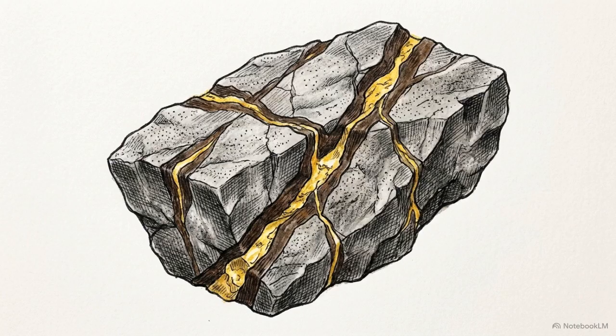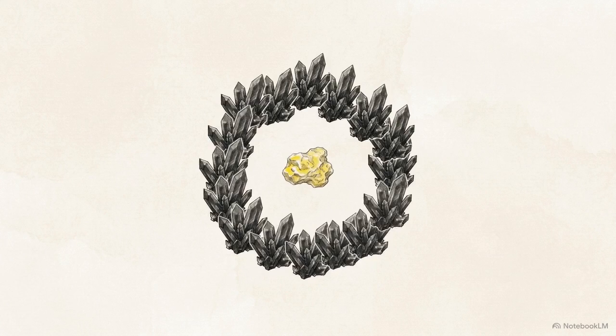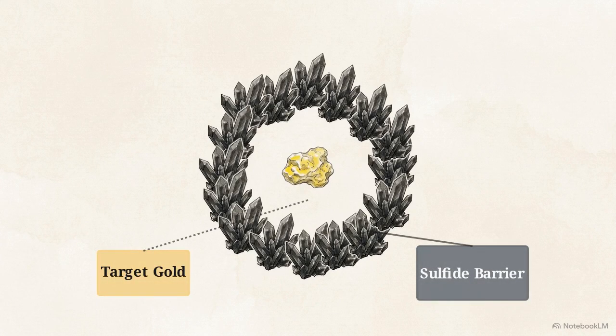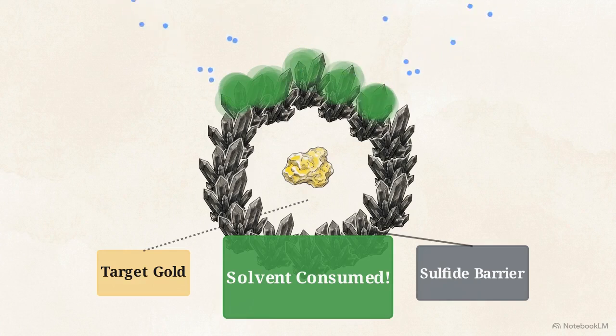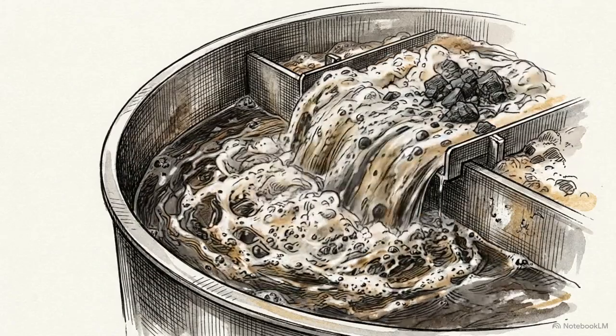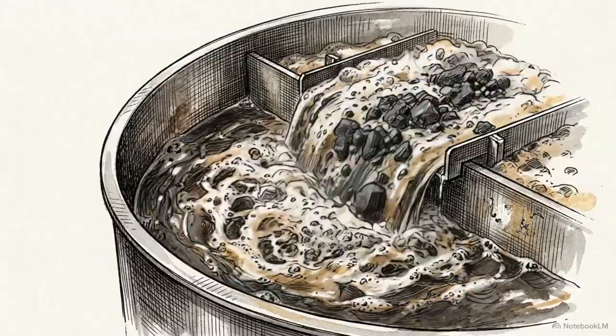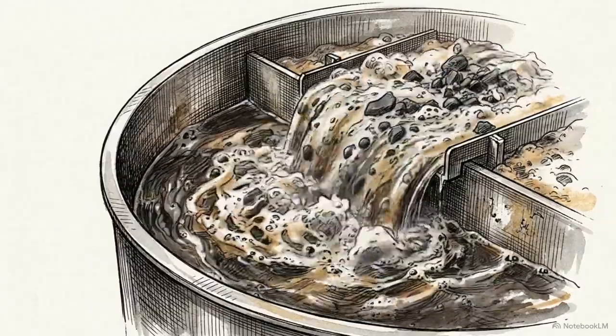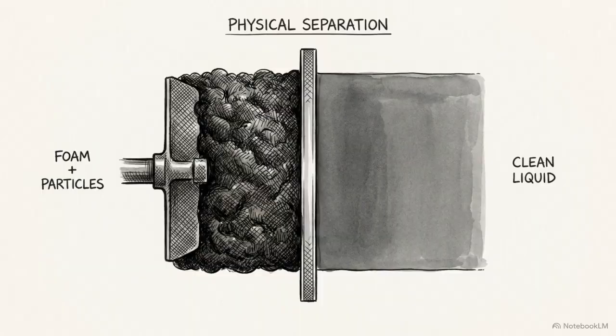At this stage, operators face their first major efficiency hurdle: parasitic minerals. Raw ore often contains high levels of sulfide or carbonaceous materials that will readily consume the leaching solvent before it can ever reach the gold. To prevent that solvent loss, operators run the slurry through a mandatory pretreatment known as the flotation process. This physically separates out the problematic sulfide minerals so they cannot interfere with the next phase.